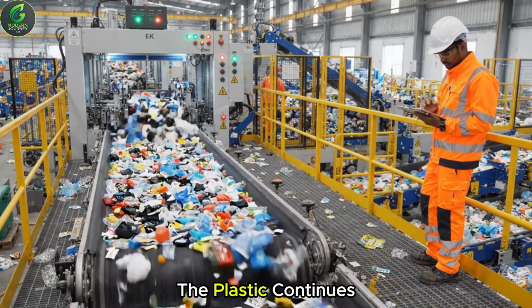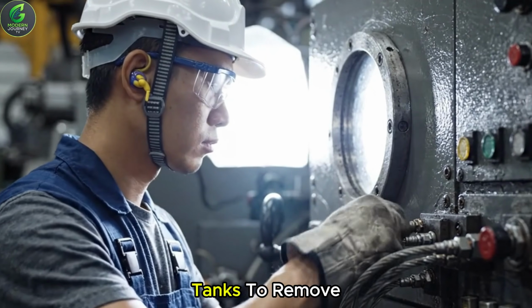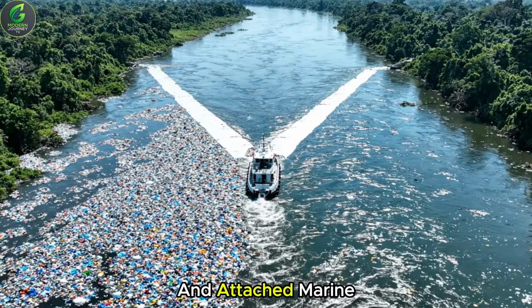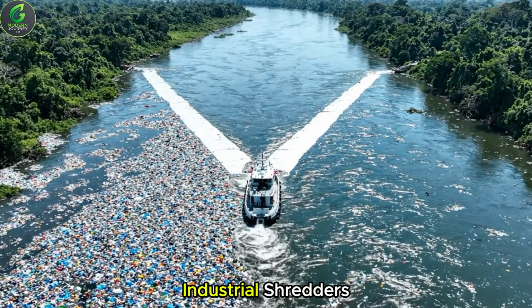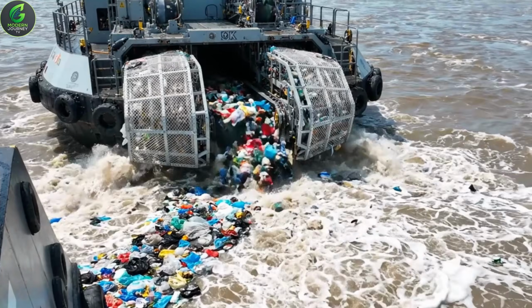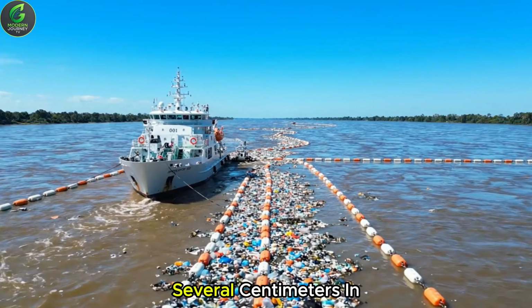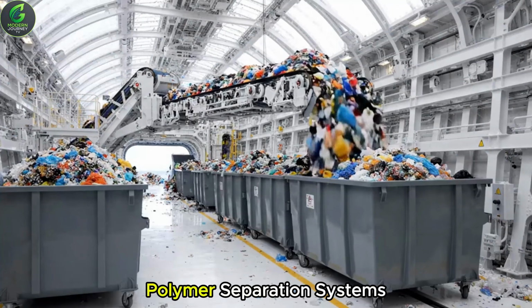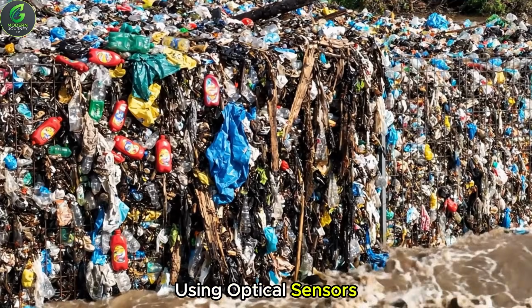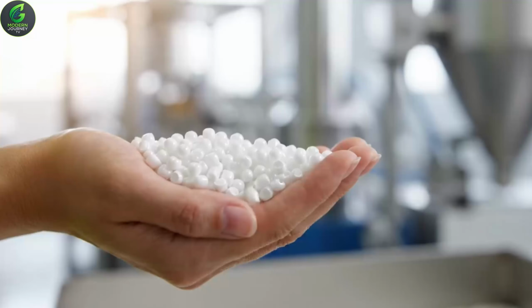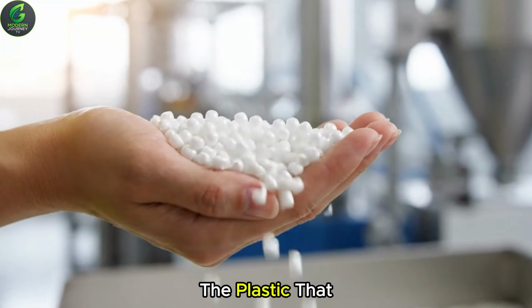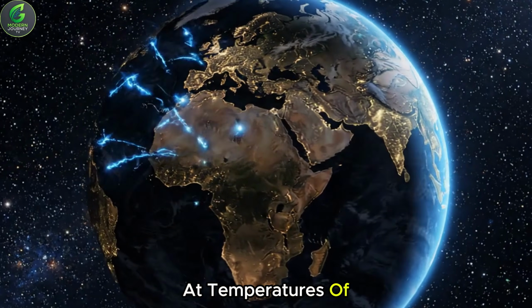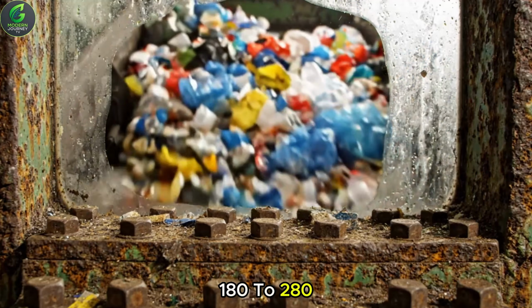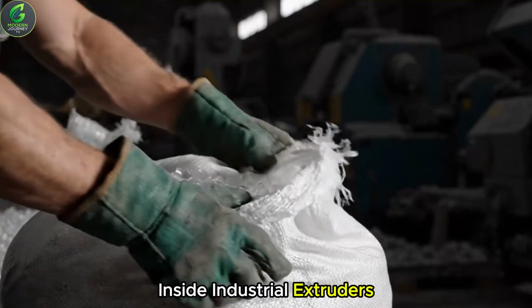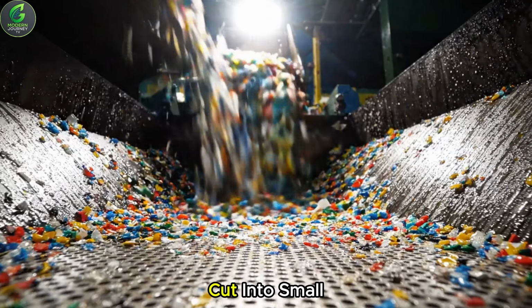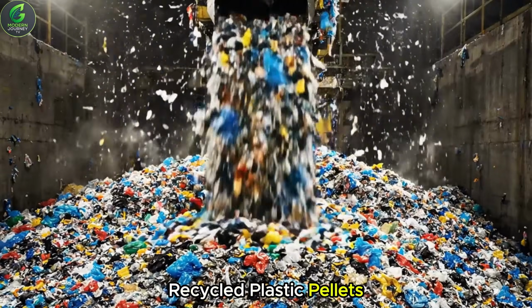After being separated, the plastic continues through large high-pressure washing tanks to remove salt, sand, oil, and attached marine organisms before being fed into high-speed industrial shredders. Here, the material is cut into fragments several centimeters in size before continuing through polymer separation systems using optical sensors and float-sink density sorting. The plastic that meets final quality standards is then melted at temperatures of approximately 180 to 280 degrees Celsius inside industrial extruders before being stretched into strands and cut into small recycled plastic pellets.